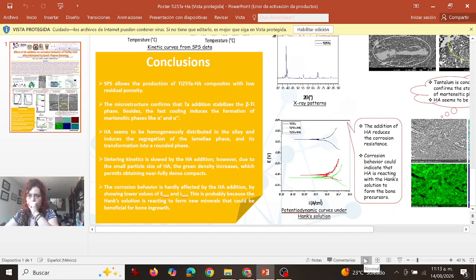All right, let me finish with the conclusions. So the Spark Plasma Sintering allows the production of titanium 25 tantalum with hydroxyapatite composites with low residual porosity. The microstructure confirms that the tantalum addition stabilizes the beta titanium phase. Besides, the fast cooling induces the formation of these martensitic phases like alpha prime and alpha double prime. The hydroxyapatite seems to be homogeneously distributed in the alloy, and induces the segregation of the lamellar beta phase and its transformation into a more rounded phase.